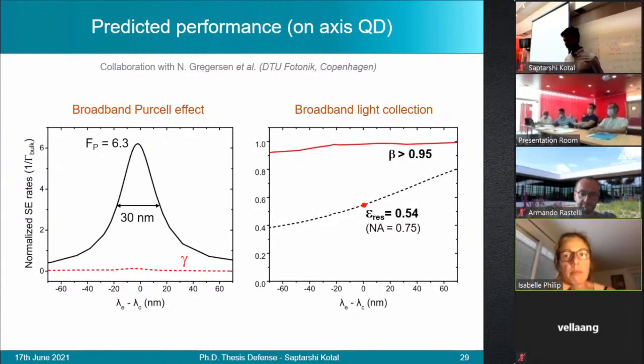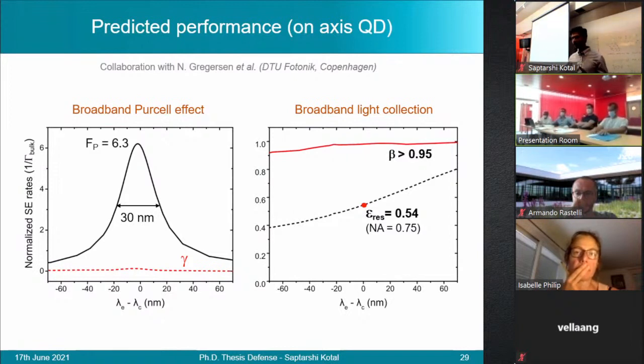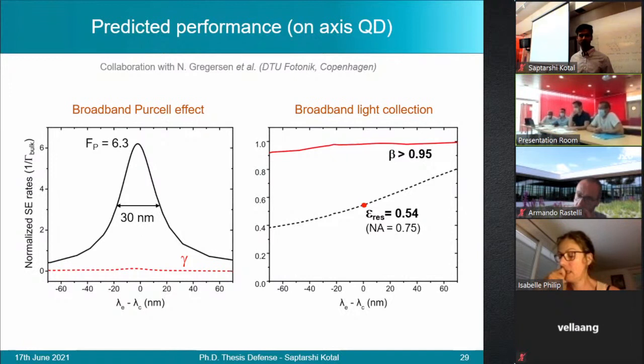Well, I think I missed something. The nanocavity, because of its dimensions, also exhibits a strong dielectric screening effect. So even though we have such an effect in the normalized emission rates, we are anyway throwing off any other possible modes. There's only the one guided mode that's left to couple to. So I would explain that the beta remains constant because it couples only to the guided mode. Whereas the lifetime varies depending on whether it's on axis or on the edge, and therefore we have a difference in the normalized rate.